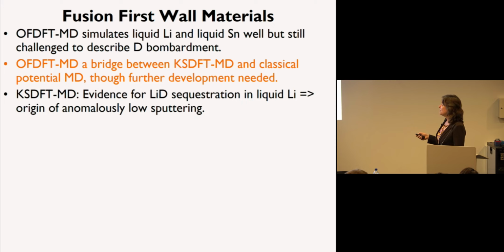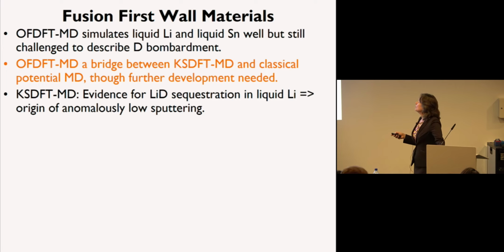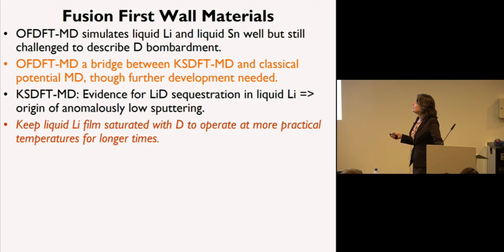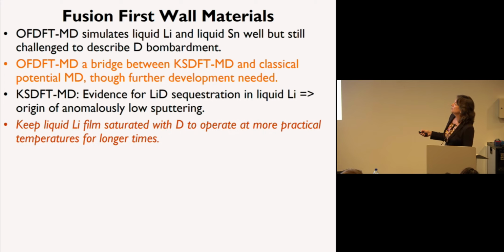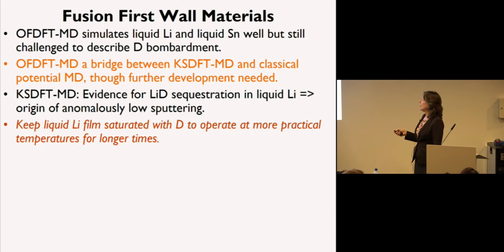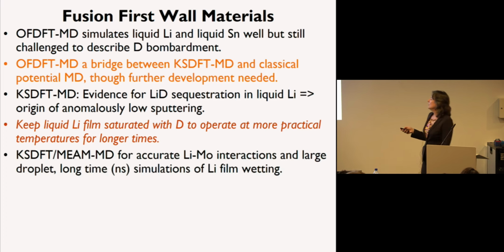From the Kohn-Sham MD, what we see is that there's evidence for a solid lithium deuteride sequestering in the liquid lithium, which is why you don't see so much sputtering under the plasma conditions. So it's a design principle: you want the liquid lithium film to be as saturated with deuterium as possible to be able to operate at higher temperatures.